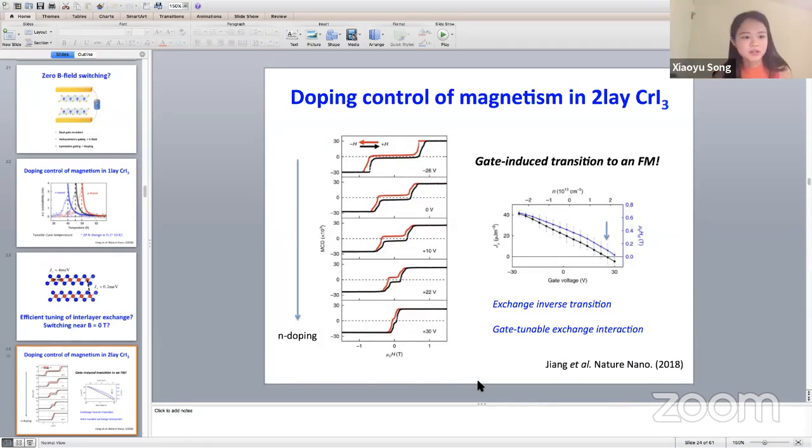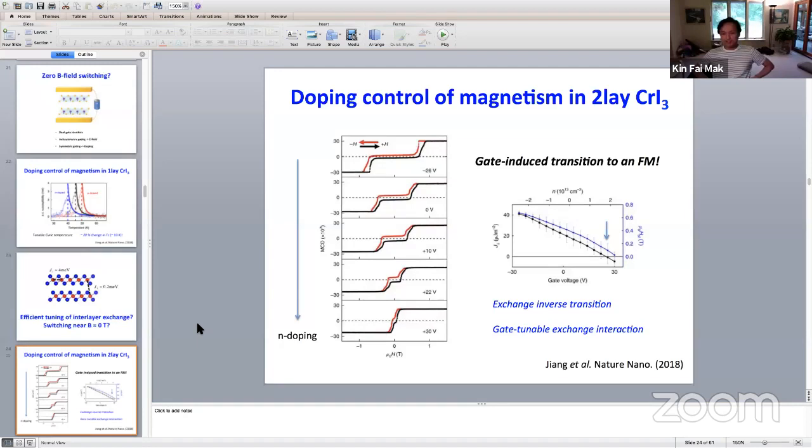And also on this slide, from Karsa: does setting J perpendicular close to 0 also ruin the stability of the magnetic state? And would it be capable of storing the information? It's interesting to think about what's happening near exactly J equal to 0 here, because effectively the two layers are magnetically decoupled. I haven't thought about whether you can use it to store information, because if the system can be randomly fluctuating, independent of each layer, it may not be very useful in terms of memory storage. I don't know, but I also want to point out one complication: even as the exchange energy goes to 0 at this point, you also have to consider the simple magnetostatic, which is basically the demagnetization field of a ferromagnet.